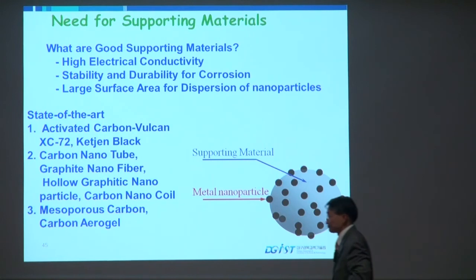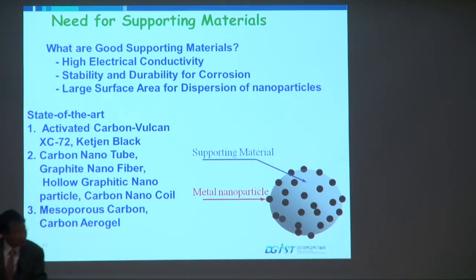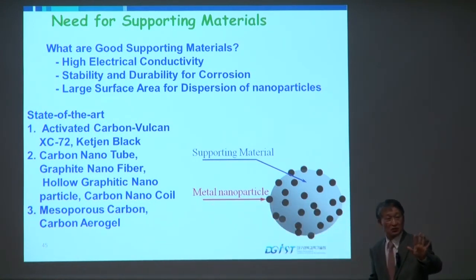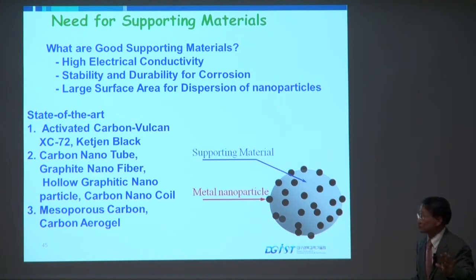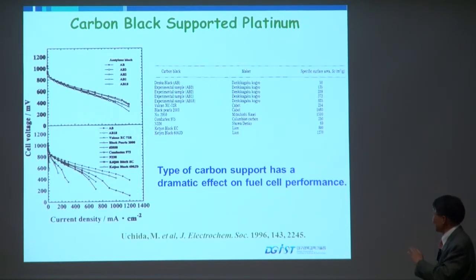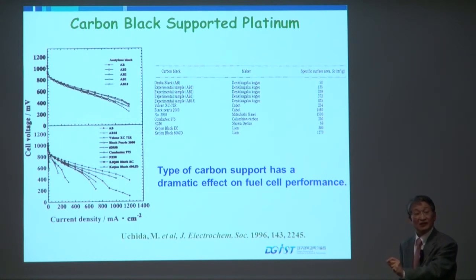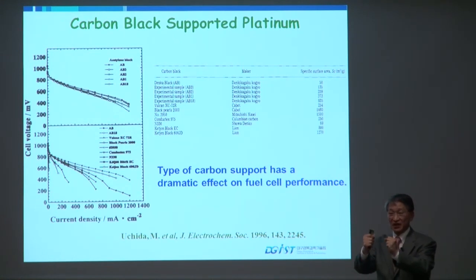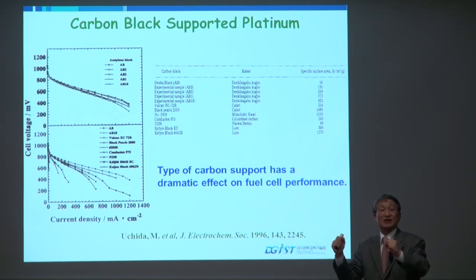Okay, the carbon support. Why do we need carbon? That's a good electronic conductivity, but also mechanical stability and durability. And different kinds of carbons, including activated carbon, Vulcan, nanotubes, and it should also include different mesoporous carbons and graphene as well. And this is another old work showing that different carbons give different catalytic activity with the same catalyst. So there is a big role of carbon depending on the interaction between catalyst and carbon. The overall performance depends very much on the carbons.